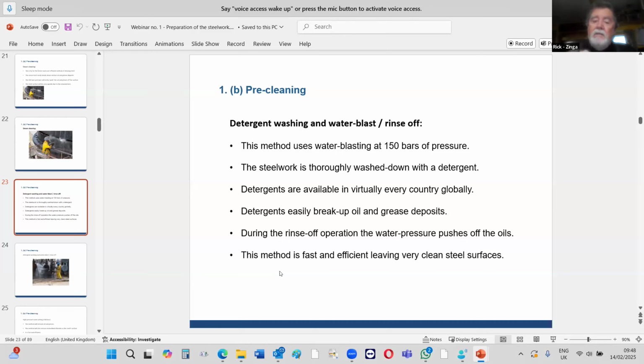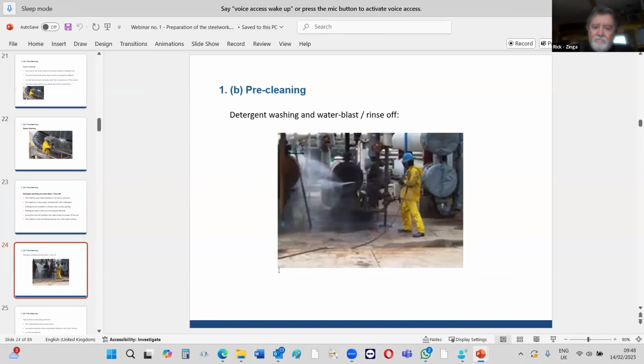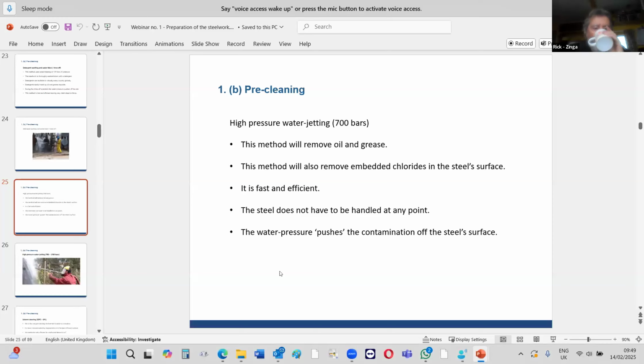If there's any residues left behind, it's high pH. And believe it or not, it can leave a micro residue on the surface. So that actually stops anything from rusting for 2 or 3 hours. So there is an advantage to having the bleach in your detergent if you're going to hold up on site. And again, all the oil and that are removed by pressure from the water jetting. That's showing you there how he's doing a rinse off.